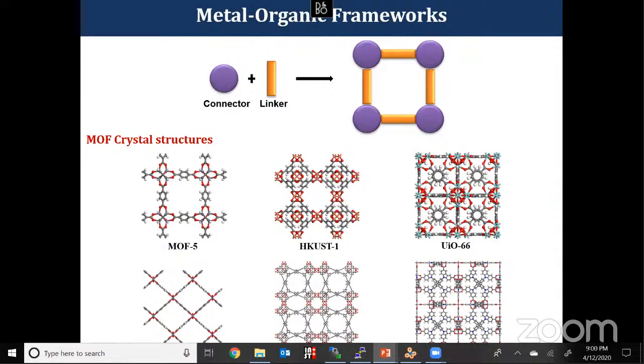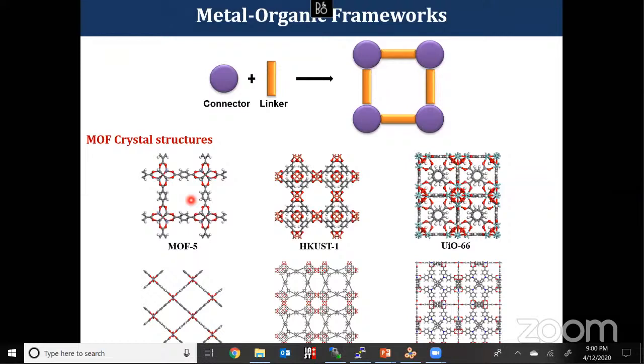Okay, metal organic framework. This field got established around 2000. The first metal organic framework synthesized is MOF5, synthesized by Professor Omar Yaghi. In their group, they synthesized numerous metal organic frameworks with various topologies. The framework has two parts: one is the connector and the other is the linker. The connector is always a metal, metal oxide, or metal cluster. The linker is an organic acid, which may be a dicarboxylic, tri, tetra, or polycarboxylic acid. In some cases they may have an azo group. Covalent organic frameworks and zeolitic imidazolate frameworks also exist, but today I'm going to talk only about metal organic frameworks.